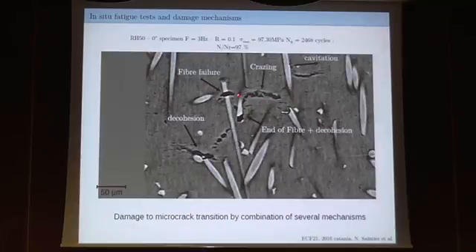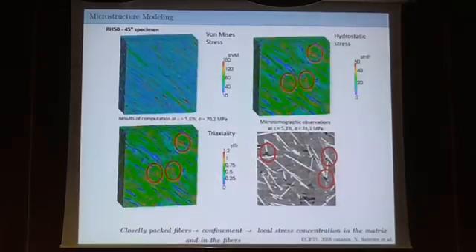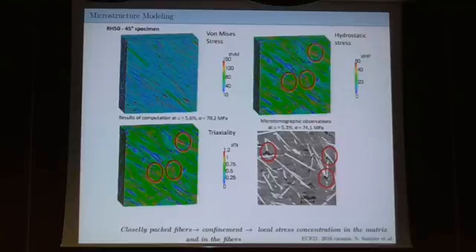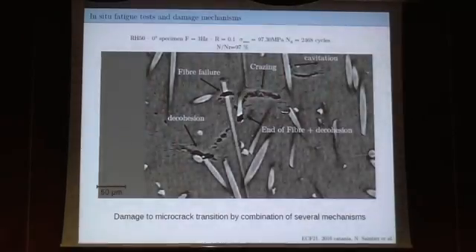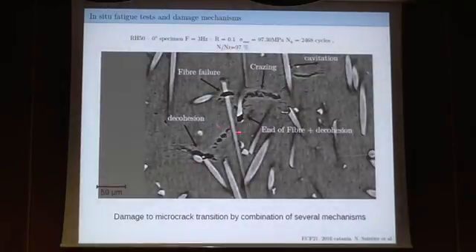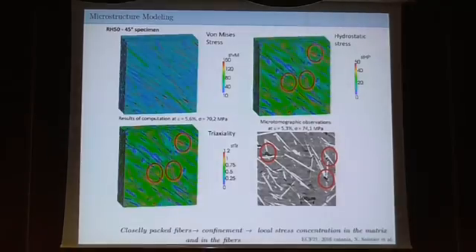And this size here is more or less between 20 and 30 micron. It's more or less the size of the spheroids. Okay, so we don't have the image of the microstructure, but we really think it's related to the microstructure behind it. So we did a little bit of microstructure modeling. I will not speak too much about it today, but our aim is more to understand why we observe such phenomena. In particular, where you have closely packed fibers, you observe these damage processes.